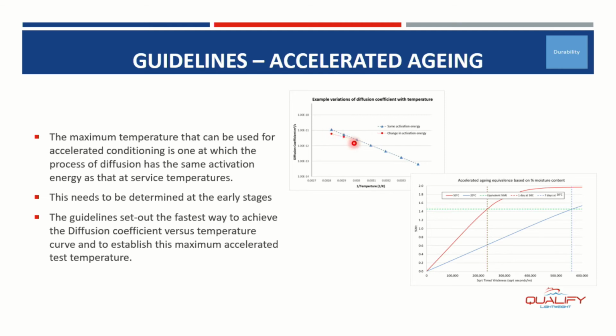If we test at these temperatures, we'll get a saturation level that isn't representative of what would have gone on in normal service conditions for accelerated time. So this is the only safe temperature, or the highest safe temperature that we can use, that we're assured is replicating what's really going on at the service temperature. Once you establish this temperature, you can then use that for your accelerated aging.